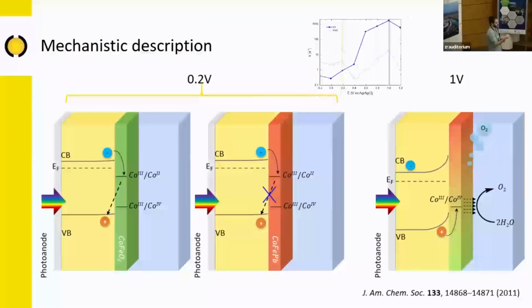So basically, just to get to the end, the explanation we had for the different trend we see in different catalysts is that in open circuit conditions, that is about 0.2 volt, where we shouldn't have any spontaneous reduction of the cobalt, upon illumination we see two different behaviors that are related to the chance of recombining these electrons transferred to the cobalt co-catalyst. In the case of cobalt iron oxide, we have that shrinking of the reduction peak, while in the case of Prussian blue, this process is not taking place. The reason is unknown, but this process is not taking place. This was also suggested by a quite old paper on a similar catalyst to be one of the reasons why the catalyst is working as a catalyst, as it is increasing the hole lifetime in the semiconductor, since there is no recombination possible in this case.